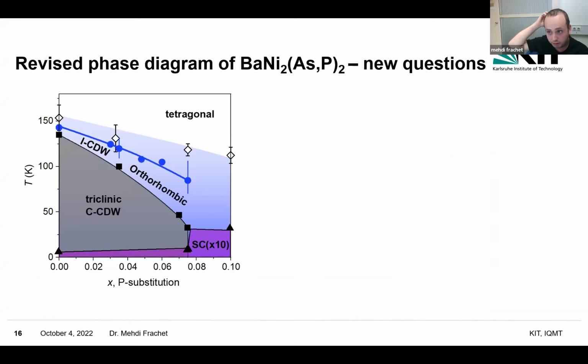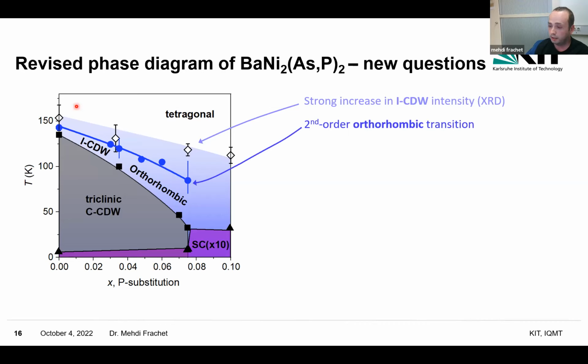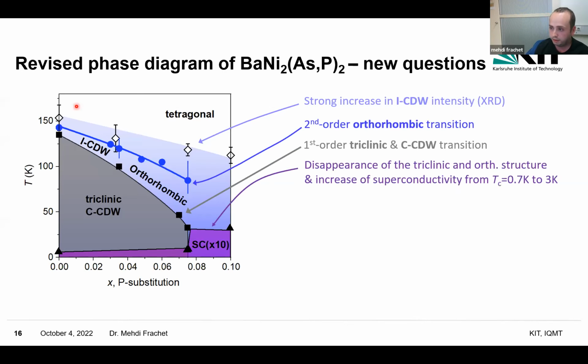So this orthorhombic distortion led us to revise the phase diagram of this phosphorus-doped barium nickel arsenide. So that's what we get now. You see, upon cooling, what we first get is this strong increase in the intensity of the incommensurate charge wave. At slightly lower temperature, you have this second-order orthorhombic transition. And at even lower temperature, you have this first-order triclinic transition with this commensurate charge wave. At very low temperature, there is this superconducting phase, and you see that there is this strong increase in superconductivity in a first-order-like fashion from 0.7 to something a bit above 3 Kelvin. I think it's 3.25 or something like that.